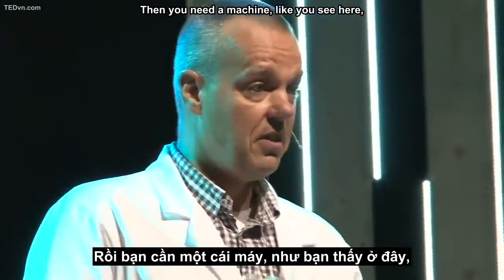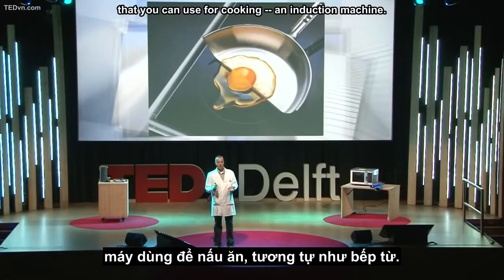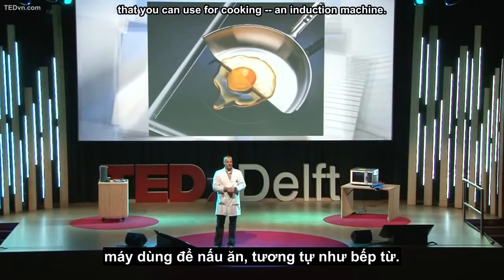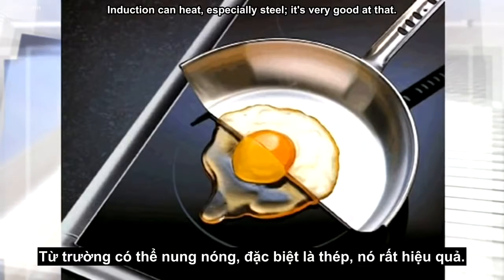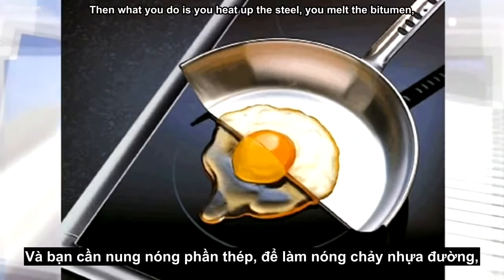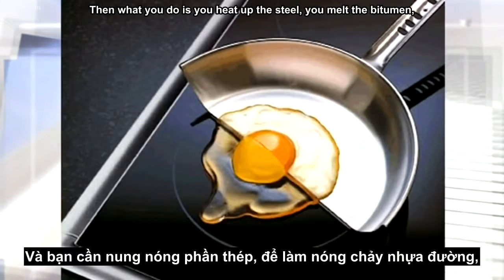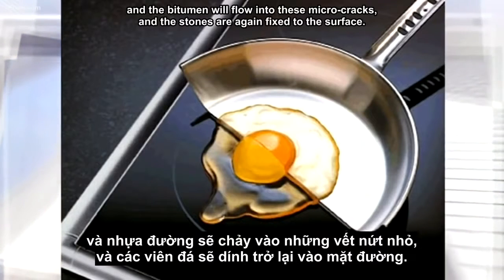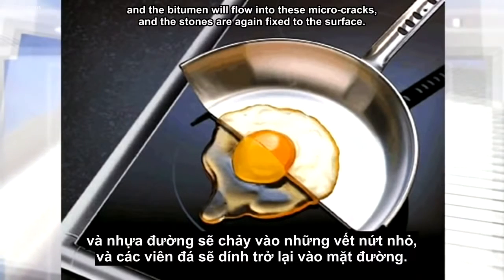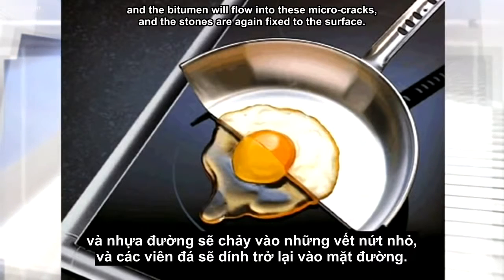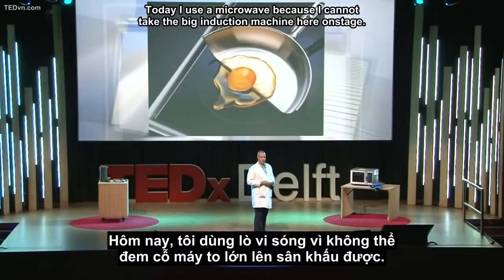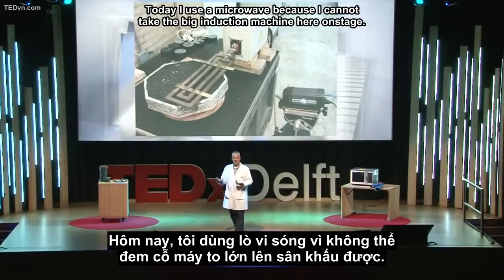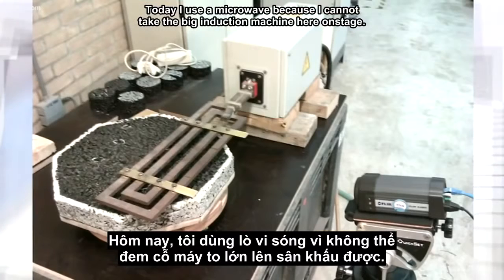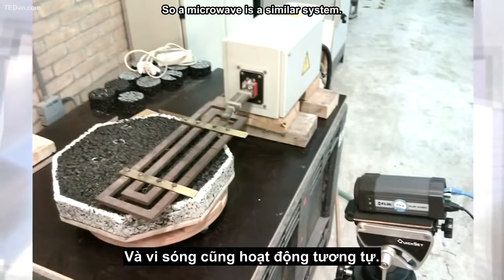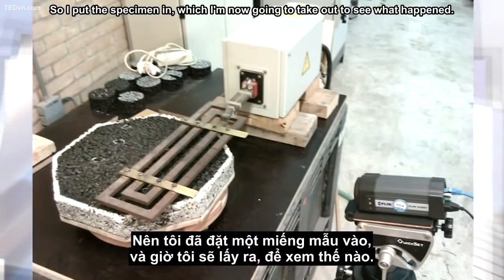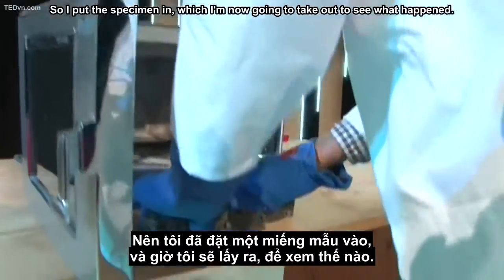Then you need a machine like you see here that you can use for cooking: an induction machine. Induction can heat, especially steel, very well. Then what you do is you heat up the steel, you melt the bitumen, and the bitumen will flow into these micro cracks, and the stones are again fixed to the surface. Today I use a microwave because I cannot take the big induction machine onto the stage, so a microwave is a similar system. So I put the specimen in, which I'm now going to take out to see what happened.